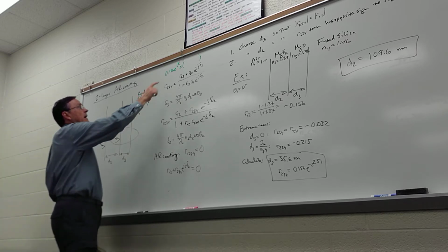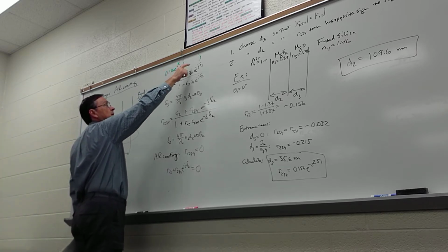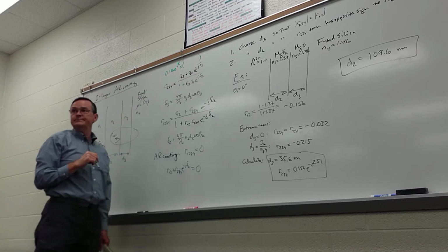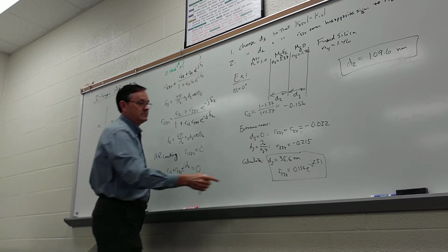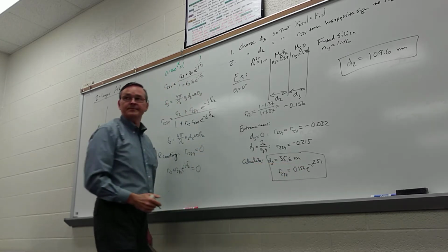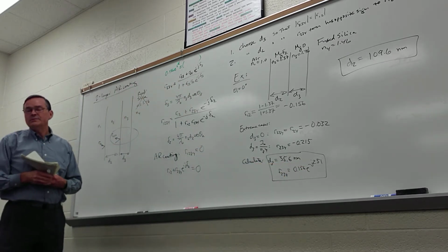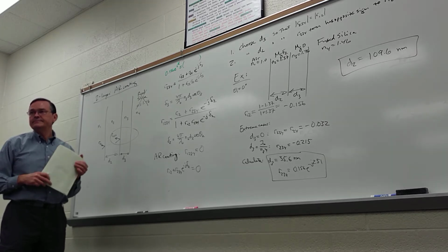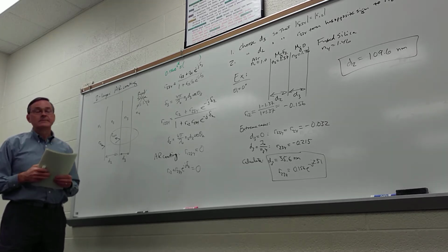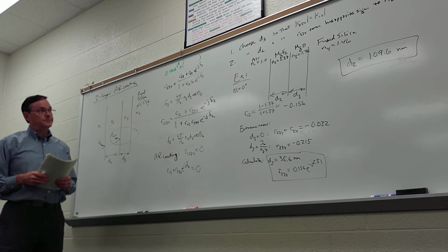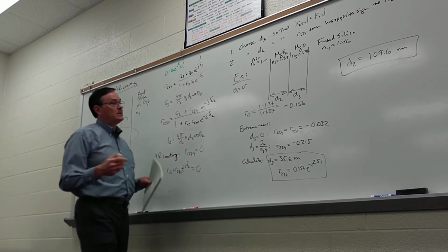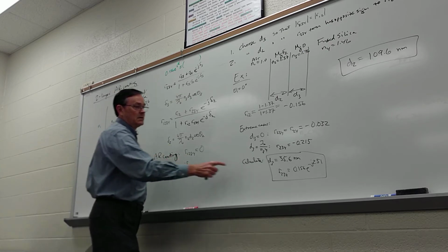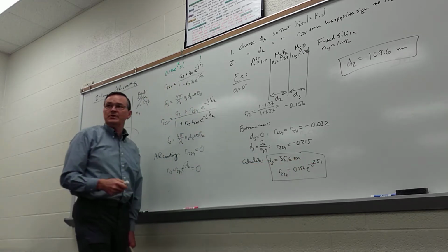And I don't care what the phase is. So basically I run through a bunch of d3s until I get that magnitude, and that's what it ends up being. So you do it numerically, not analytically. And then D2 is simple. You're just looking for this to equal 2.51 radians.